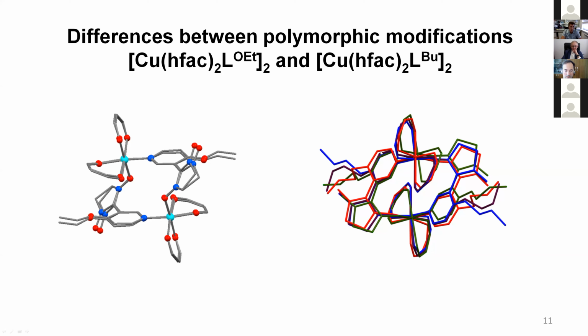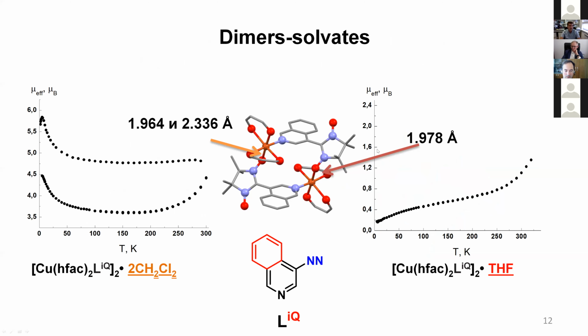and we have no magnetic measurements, because it always forms in a mixture of phases, so we cannot do it. In the case of isoquinoline nitroxide, after many attempts of synthesis, 2 complexes with solvate molecules were obtained. In this structure with dichloromethane, 2 molecules with different geometries of the coordination environment of copper atoms are